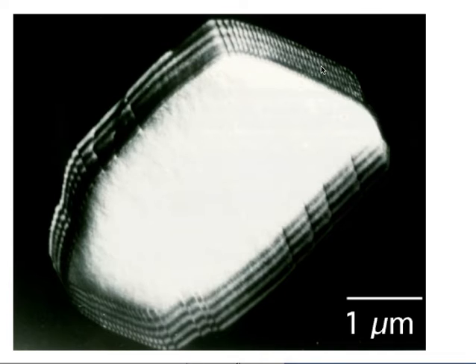Of course, it's a simple interface that we've created because we have tilted by only one axis. In general, you can describe the misorientation between two crystals with three Euler angles. In other words, you can put a general rotation, and then you may see more arrays of dislocations in the interface, non-parallel arrays of dislocations. But the contrast is coming from the fact that these dislocations have a strain field.